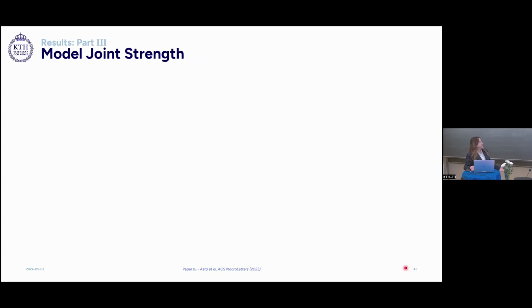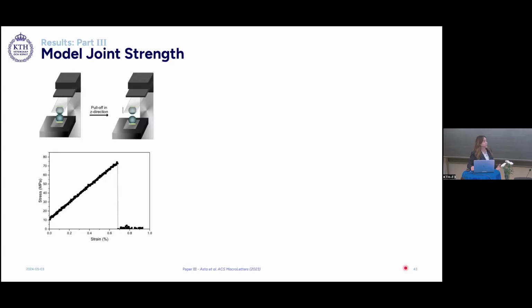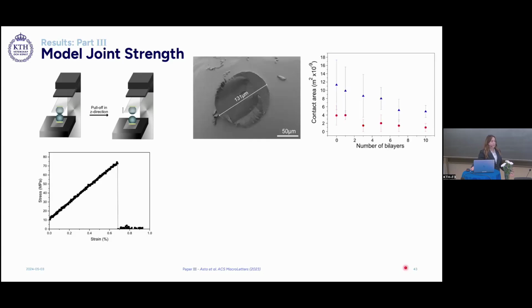Now, to examine the adhesive properties of these model cellulose joints, we performed pull-off measurements using our contact adhesion tester by pulling off the beads in the joint in the Z direction. The stress at break was obtained by normalizing the pull-off force with the contact area, which was measured after separation of the two materials.